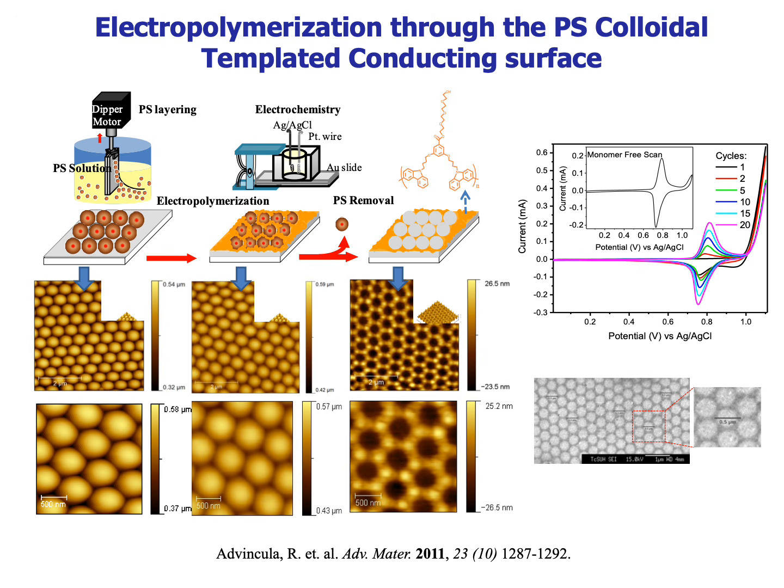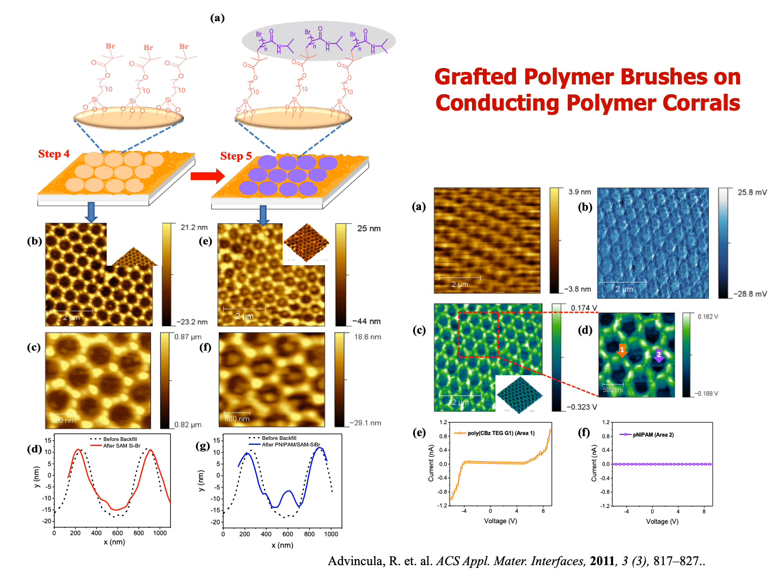We can then utilize the space inside those holes by depositing, let's say, a self-assembled monolayer film of macro-initiator polymers, where the macro-initiator for ATRP polymerization was first grafted on the surface, followed by grafting a poly-NIPAM or poly-N-isopropyl acrylamide brush, as shown here. So this resulted in lines and a height profile representing that of the grafted brush.